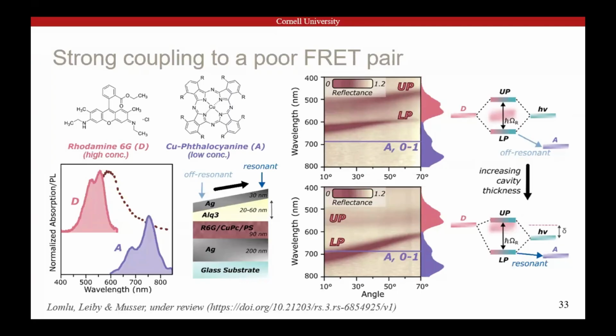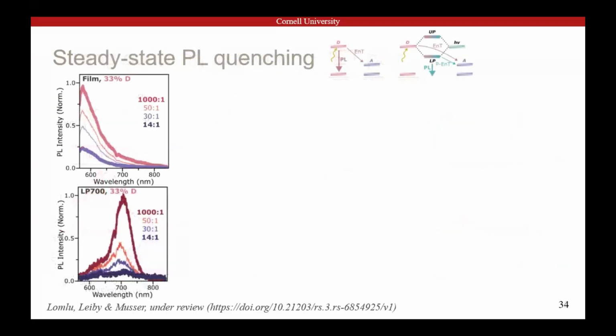Polaritons are made of photons, so they want to emit light. So the easiest way to check if they are being quenched is to check the polariton emission. If we look at our thin films, as we increase the concentration of acceptor for this 33% donor loading, the rhodamine yield progressively decreases, as typical for a poor Förster pair. When we put it into the cavity, we see exactly the same behavior. Strong polariton emission when there's basically no acceptor, highly quenched when there's a lot of acceptor. And if you look closely, you can see this degree of quenching is larger in the cavity than it is in the film. And this is the first sign that it's not just the dark states inside of the cavity that are transferring energy, because that should happen, but there's something more going on when we put it in the strong coupling regime.